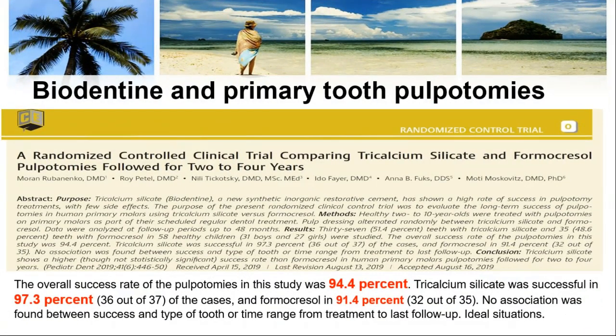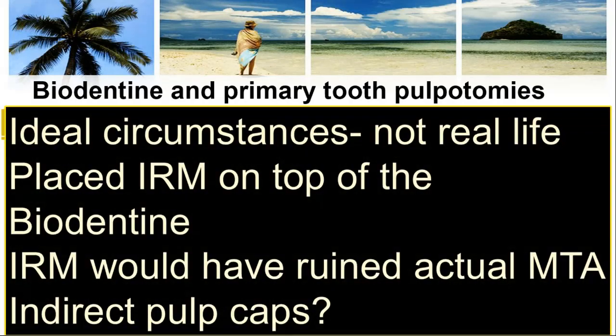But it does well, and this is published in the Journal of Pediatric Dentistry, published just in August, I believe it was, 2019. It was a comparison between Biodentine and formocresol pulpotomies. They followed them for 2 to 4 years. And as you see, they had a very, very high success rate. With their Biodentine, they were at 97.3%. And their overall rate was 94.4%. That's really, really good. But I would have to always explain to people, this is a clinical trial. They're looking for ideal situations, and that's not what you find in real life.